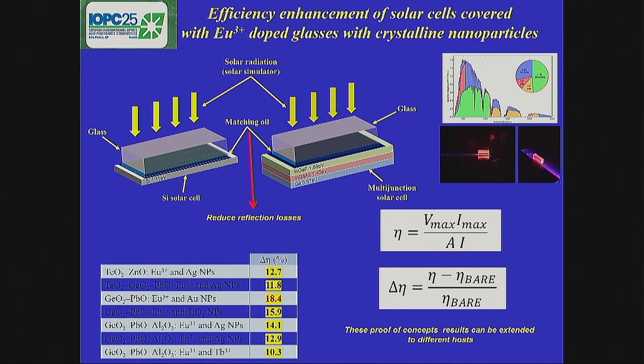And then in this table, I show you the more important results. As you can see, we use different nanoparticles, metallic and dielectric ones, silver, gold, and titanium. I think that titanium cannot be seen here, sorry. And then we calculate the efficiency in all the situations, and the best result was found when we used gold nanoparticles, with an efficiency enhancement of about 18%. The efficiency is calculated using the electrical parameters, voltage and current at the maximum power, the area of the solar cell, and the irradiance. And the efficiency enhancement is calculated by comparing the efficiency of the solar cell with that of the uncovered one.